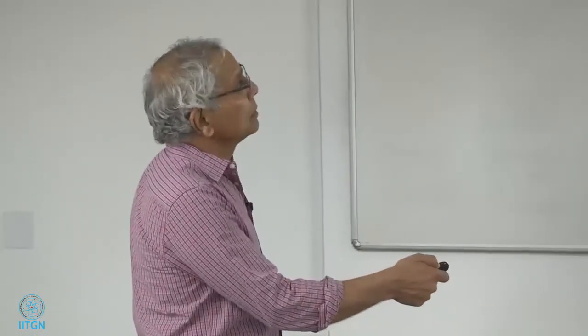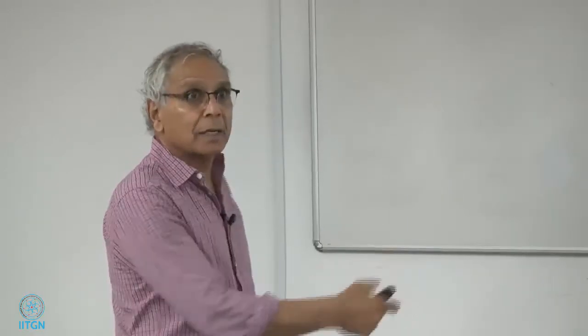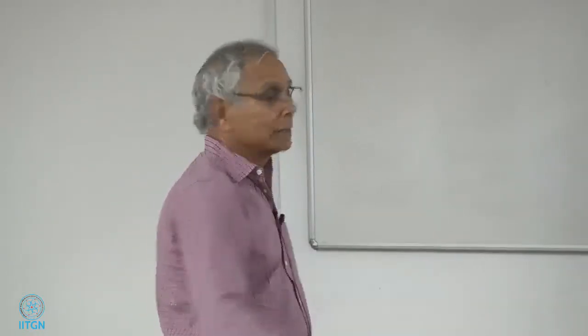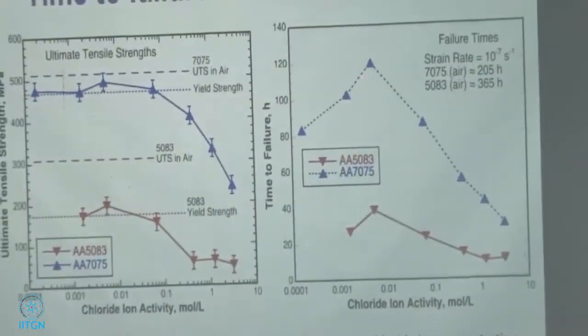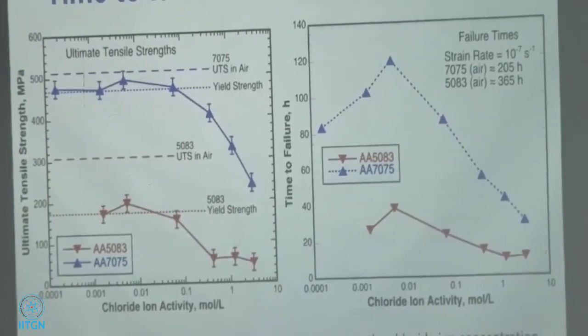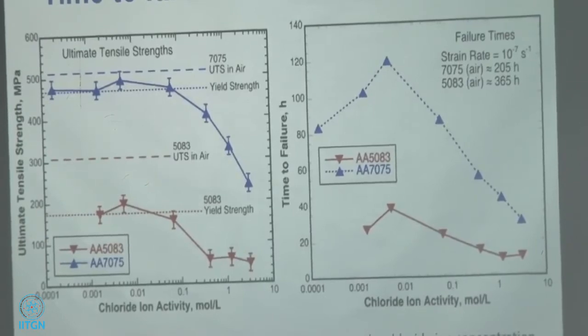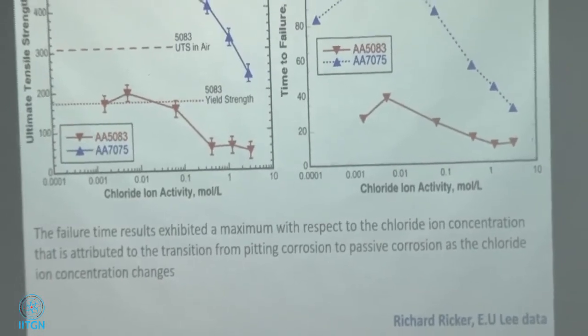But if you want to see the effect of environment, like chloride ion concentration or relative humidity, for example, those two come to my mind when it comes to aluminum. And if it's titanium, maybe it's methyl alcohol or something like that, where it attacks. But you have to run it at a slow strain rate so that there is time for the ions to react, right? So it goes up and then comes out. This is because they exhibit a maximum with respect to chloride concentration.